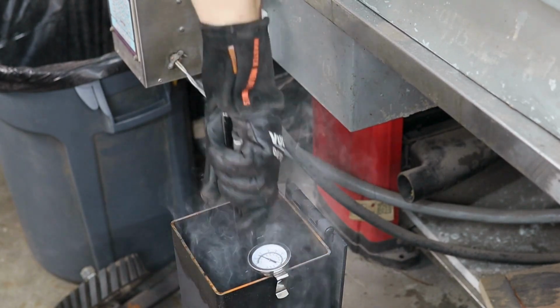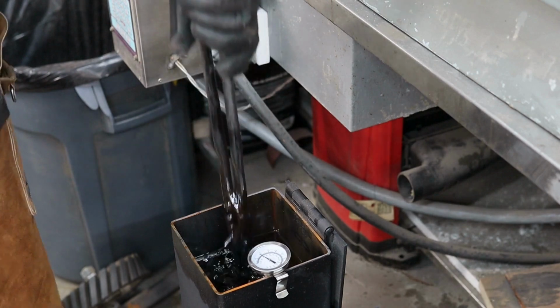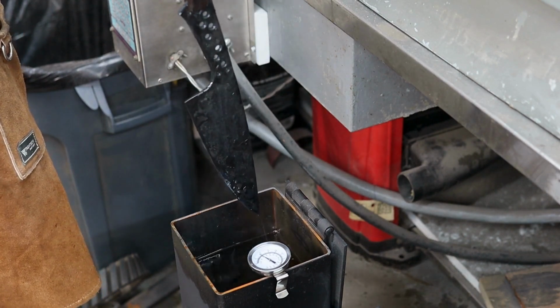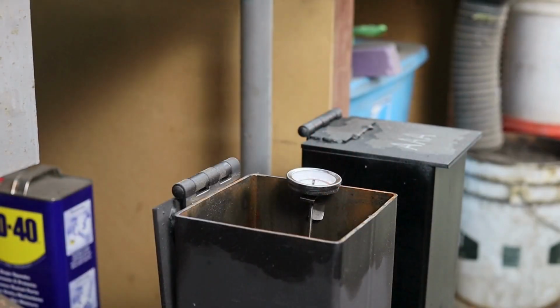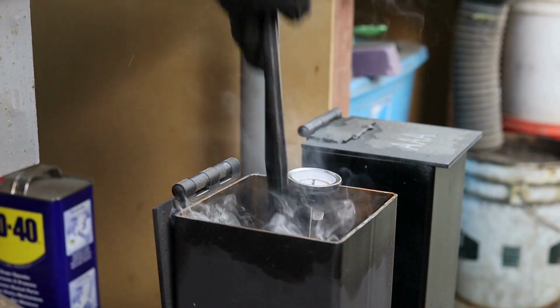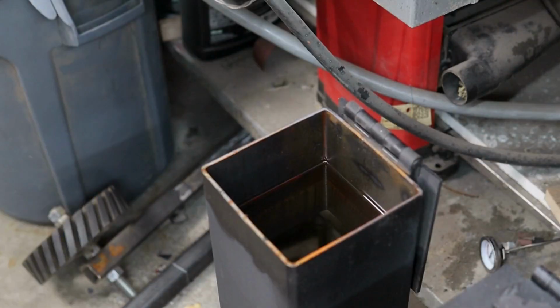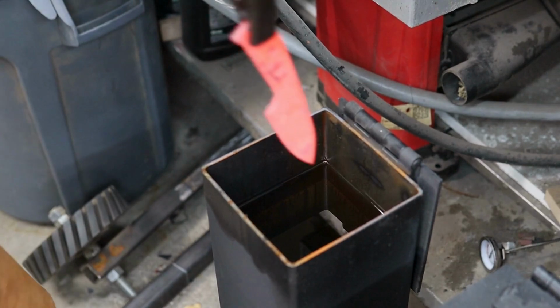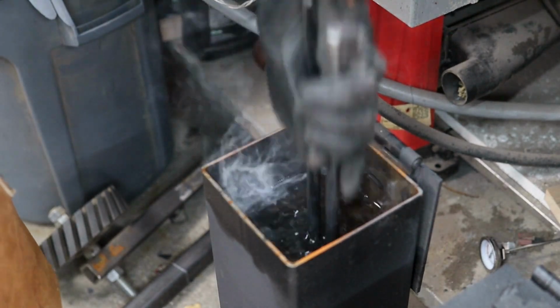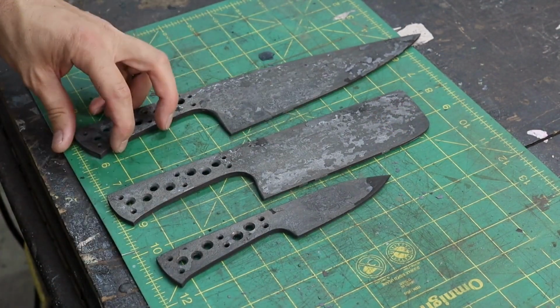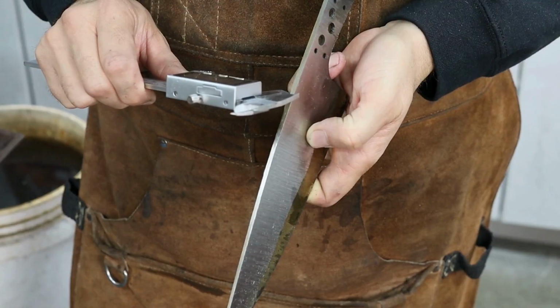completely dissolve the carbides and they're able to move freely throughout the grain boundaries in the steel. The hotter and longer that you expose the steel to high heat, the larger your grain growth will be. Because of that, in my first cycle at 1650, I want to heat the blade high enough to ensure that I've completely dissolved the carbides. This will allow the carbides to more uniformly distribute throughout the steel along the grain boundaries.